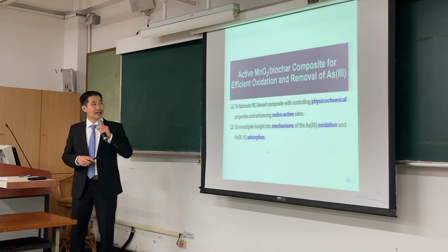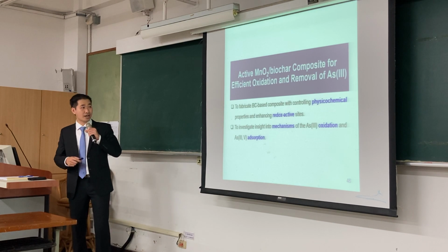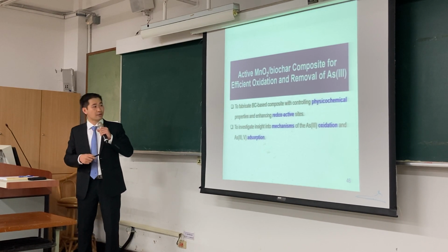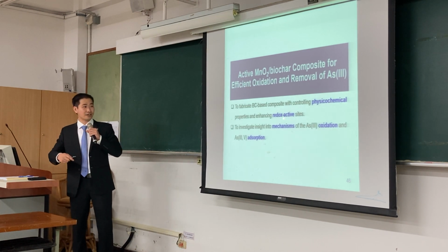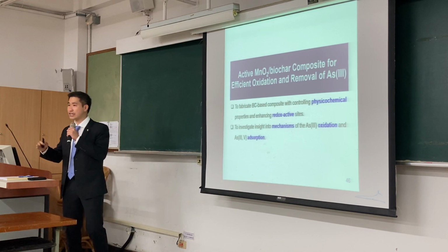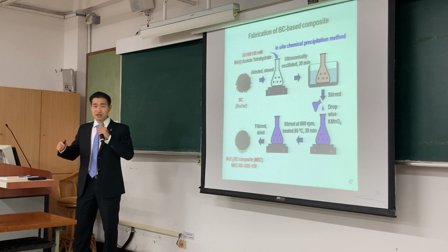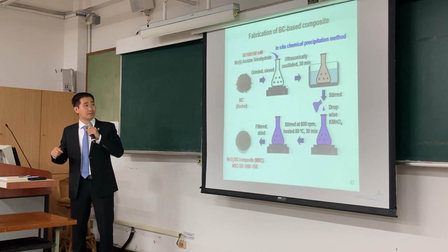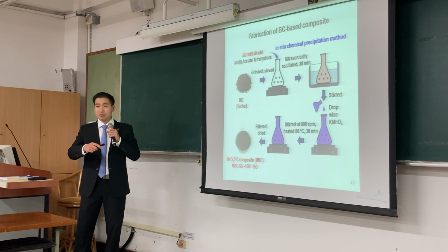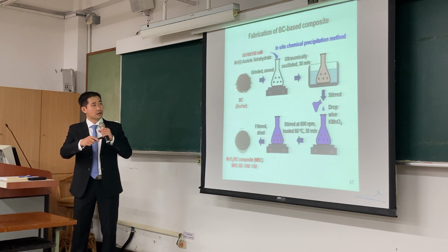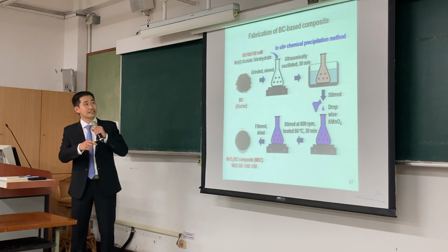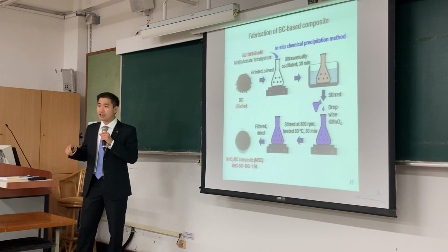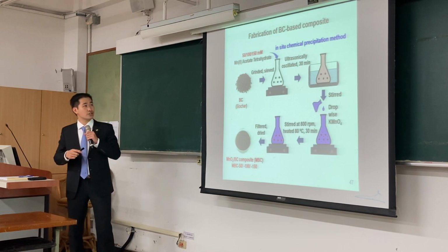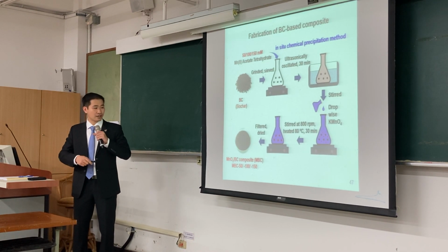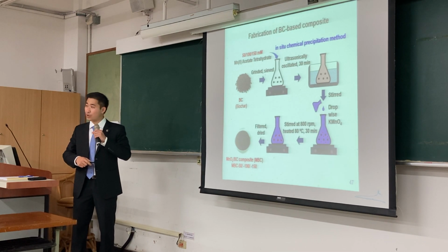In my third scope, manganese dioxide biochar composite was prepared to enhance the physicochemical properties and enhance the reactive sites. To investigate the insight into the mechanism of arsenic(III) oxidation and arsenic adsorption, the BC-based composite material was prepared by coating manganese dioxide on raw biochar using an in-situ chemical precipitation method. Here, I changed the concentration of manganese solution. Finally, I obtained the MBC 50, 100, and 150.